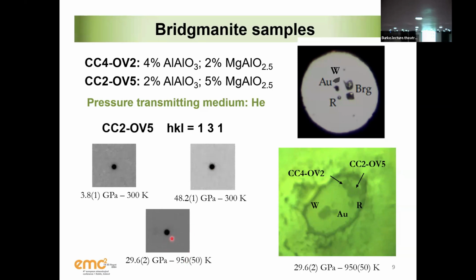We could collect up to 350, 370 unique reflections, not total reflections, unique reflections. So we could do all the refinement in anisotropic, and we could have a discrepancy factor less than 3.5% for all our data, except the bad one, but that one we threw away.